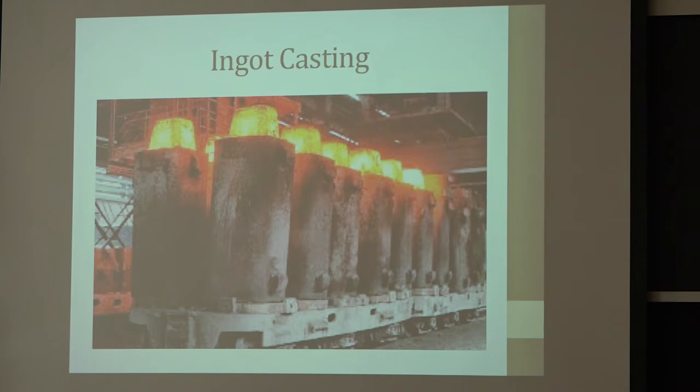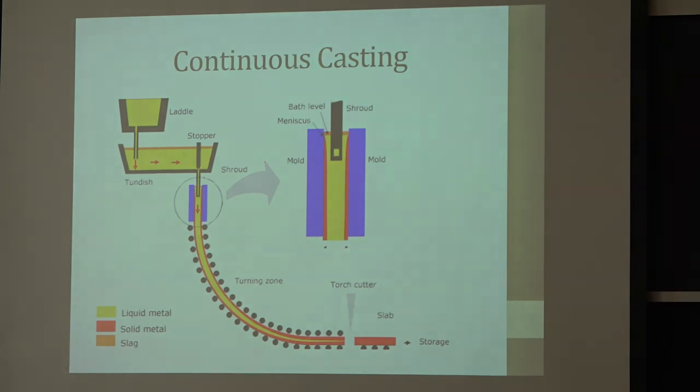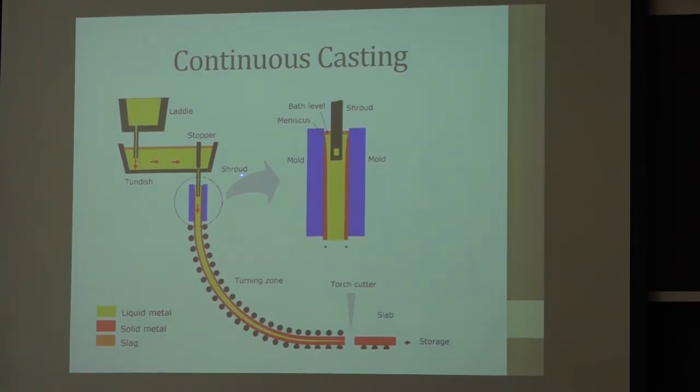Some people, again I think it was Austria, decided they could try continuous casting. Continuous casting had been done on lower temperature metals like brass, copper alloys. They were doing it on gold alloys which is not all that different than brass. In continuous casting you have a ladle with molten metal that you melt somewhere else. You pour it into something called a tundish which is just a bathtub holding things, and it drops the metal into a mold. The mold is water-cooled copper. You will solidify a little skin on this and in this yellow band you actually have molten metal. The whole thing is pliable so you have these rolls. This whole thing stands about seven stories tall. You have liquid metal in the center. If you get a breakout, it takes about a week to clean it up because you've got 300 or 400 tons of molten steel hitting the floor.